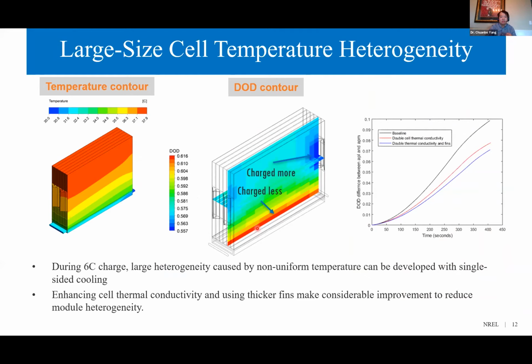This 3D model captures the heterogeneity caused by non-uniform electrical and thermal fields, with a 3 parallel 2 series connected cell with a liquid cooled plate. It was found that electrode close to the tab area was preferentially used during charge. This is because of the higher electrical potential and also because of the higher temperature, where usually the cell has a lower resistance.